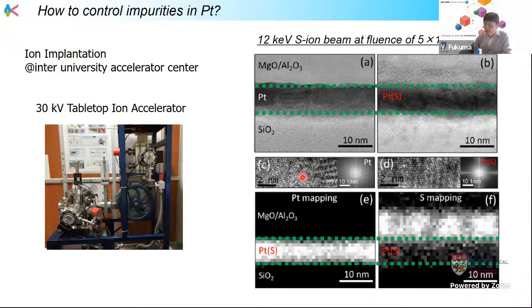What we can see here is the cross-sectional TEM image. We can see no strong degradation of the crystallinity in the platinum layer, because we use sulfur, a light element. That's why we can inject the impurity with a lower acceleration voltage, and so there is no strong damage to the crystal properties.